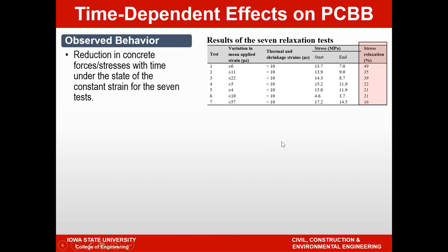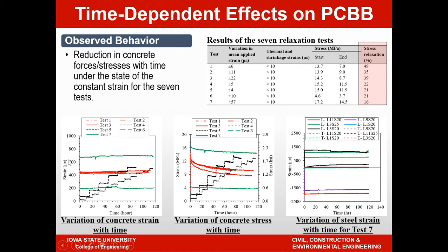We then looked at the different tests. I'm showing you the strains, the stresses, and the strain gauge data as well. So let's start with the very first figure, on the left, which shows the strains were kept constant if you look at the green line, and that was our motive to perform the relaxation test. The black line shows a step function.